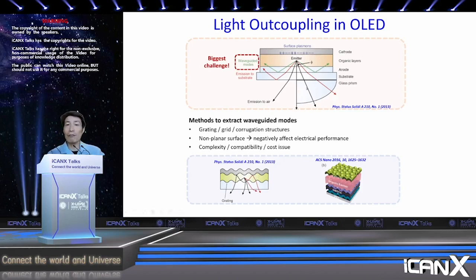We're thinking if we replace the ITO with thin silver, because it's very thin and silver, the index is very low. In fact, the real part of the index of silver is close to zero. So we should in principle eliminate, right, or reduce this waveguiding property. And that's in fact what we did in a previous work using a polymer emitting device material, the super yellow. You can make these multi-layer structures. You can see that compared with the ITO device, the efficiency is higher, right?